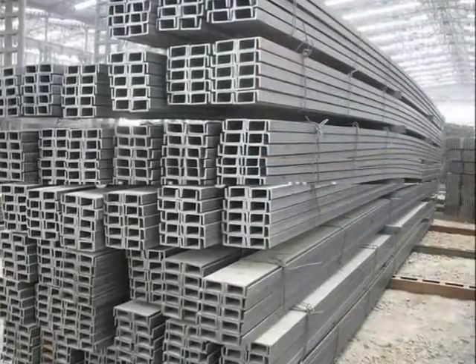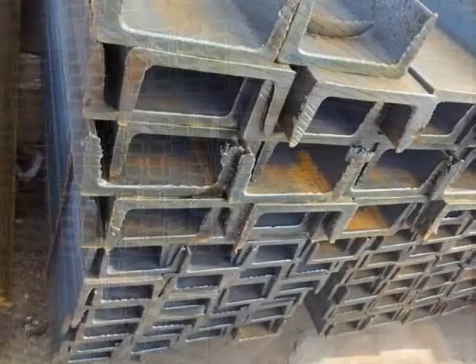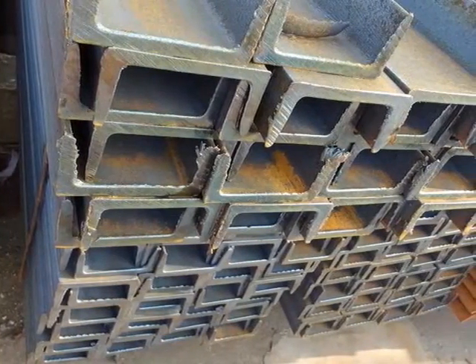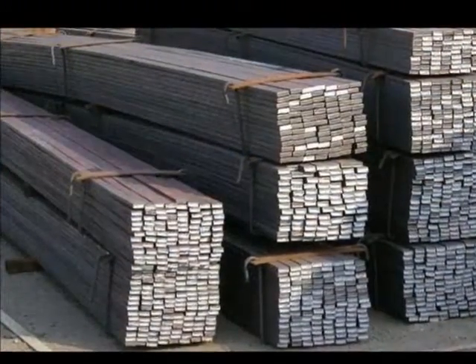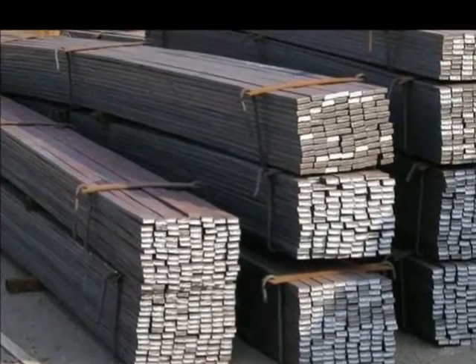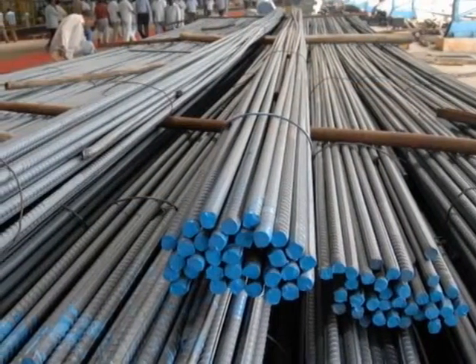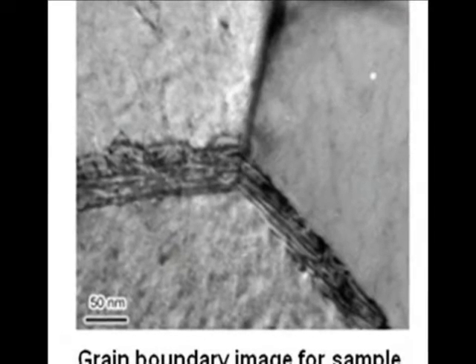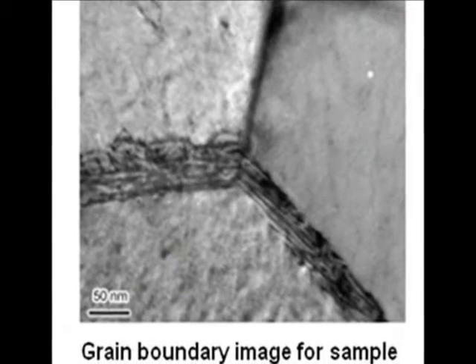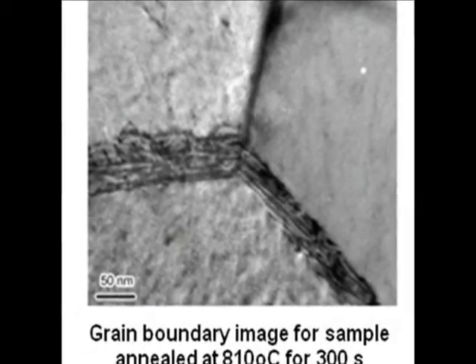However, this class of steel affords very little flexibility on the element phosphorus. Phosphorus content should not exceed 0.03% for seismic and heavy-duty structures, up to 0.06% for general-purpose construction. During post-aging of steel, phosphorus has a tendency to migrate to the grain boundary, causing severe loss in strength and increase in ductile-brittle transition temperature.